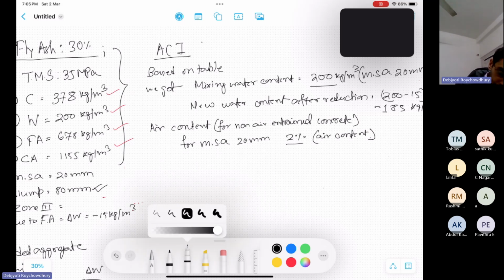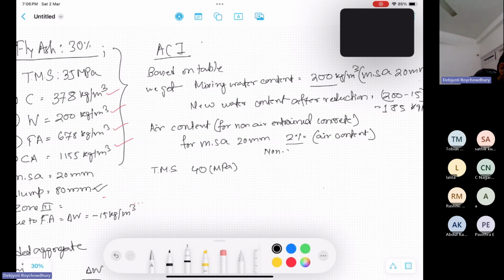Actually, for non-air-entrained concrete and air-entrained concrete, both tables are there. For air-entrained concrete, we have to interpolate. These tables are based on the cylindrical strength, and the values they show in the table are more likely our mean strength. Mean strength is already provided here as 35, so it is between 25 and 40. For a target mean strength of 40, the table says 40 MPa. This table was already mentioned in our previous class; if you have your notes, you can check these values. So for non-air-entrained concrete,